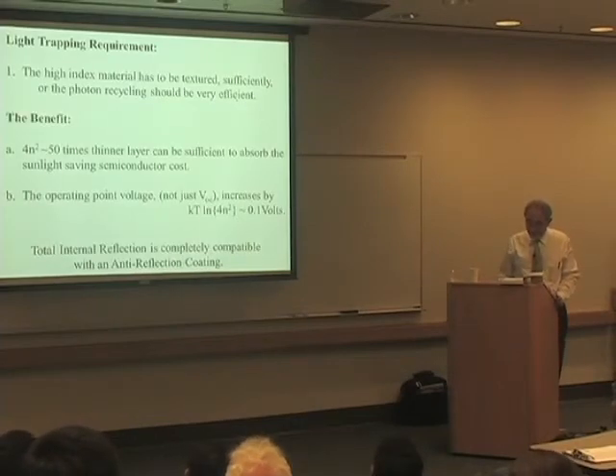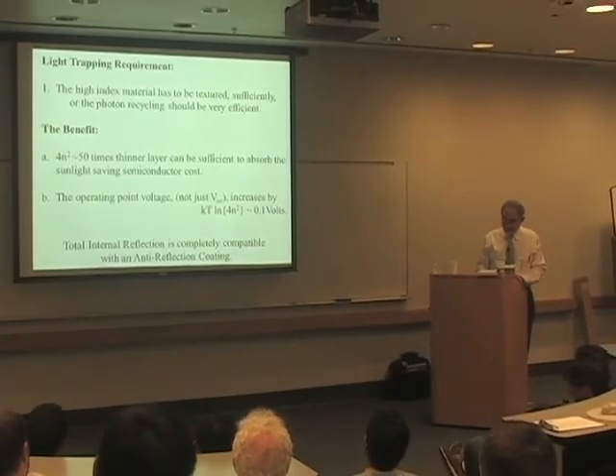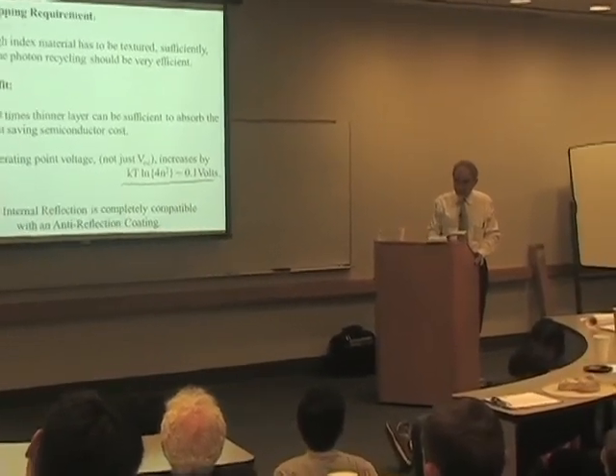So let's see. This is something I said before regarding the voltage increase, this 4n squared factor. So this is about light trapping. Let's go beyond light trapping. This gives you an idea of what to expect. And the lesson here is that it's very important to have a good mirror. So this is a bad mirror versus a good mirror, and a very big leap in voltage from 1.08 open circuit to 1.15. I'll show you the actual experiment. The experiment is even more dramatic. What do you assume for the internal quantum efficiency? This was an ideal calculation of a 100% internal quantum efficiency. And the good mirror was a 100% mirror, and the bad mirror was a 0% mirror. So I hate to show a table. I tell my students never show tables.